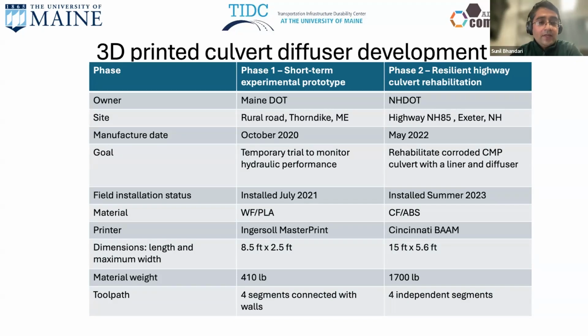We used wood flour PLA bio-based material, and the printer used was the large format Ingersoll Master Print 3D printer. The part was 8.5 feet long and 2.5 feet wide at its widest point. It was around 410 pounds of material. It was divided into 4 segments, and we printed 4 of them at once.